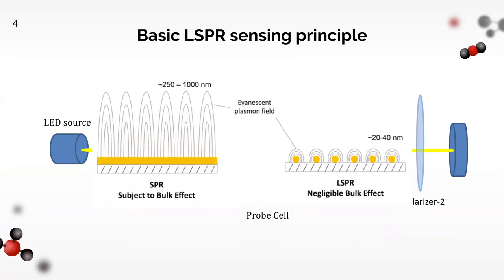Therefore, any changes in the environment, such as the binding of biomolecules to the surface of a metal film, will change the plasmon mode. You may also notice that the discrete structure confines the SPP at various surface regions. Therefore, we call it localized surface plasmon resonance (LSPR). As you can see, its sensitivity to the surface condition is even higher than SPR.